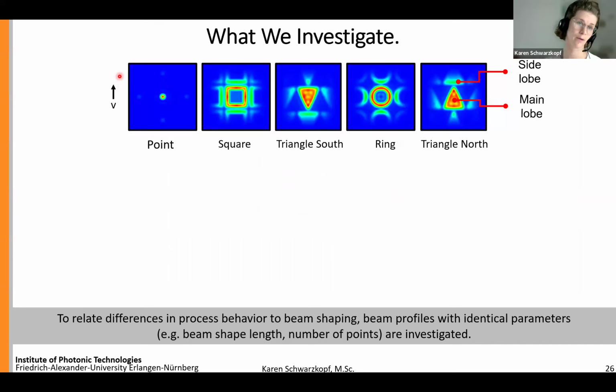As already mentioned, we combined 5 different beam shapes, and the order of sequence was as follows. As initial beam shape, a point was employed solely as a reference compared to a Gaussian intensity distribution that is conventionally used. Next, a square-like intensity distribution was employed, as it was reported in literature that a homogenization of the temperature field can be achieved by that, followed by a triangular shape where the tip of the triangle is directed opposite to the feed direction. This is followed by a ring shape, and then a triangle shape that is located in the opposite direction, namely the tip is facing into the feed direction.